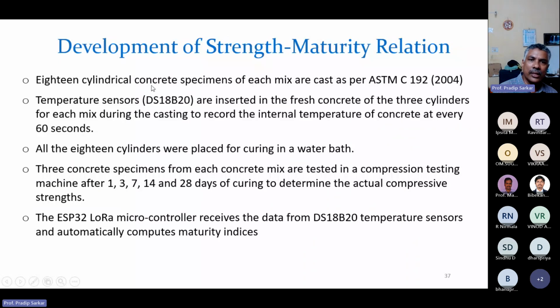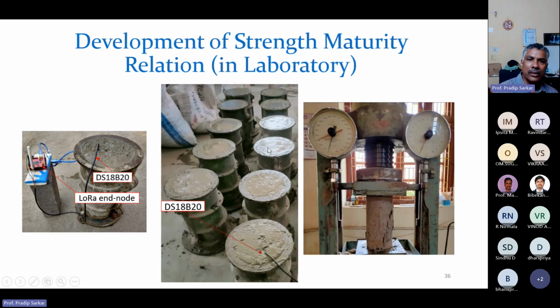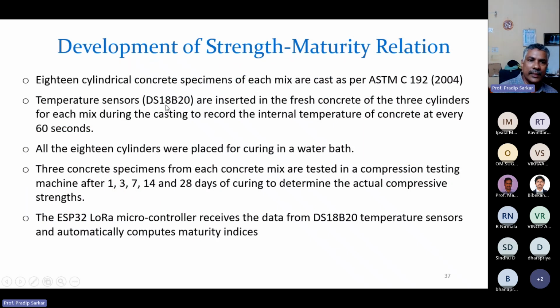So 18 cylindrical concrete specimens of each mix are cast, and temperature sensors are inserted in the fresh concrete for 3 cylinders. The maturity data are received from these 3 cylinders, and the average maturity data was recorded. All the 18 cylinders were placed for curing in a water bath. 3 concrete specimens from each mix are tested in the compression testing machine after 1 day, 3 days, 7 days, 14 days and 28 days of curing to determine the actual compressive strength.